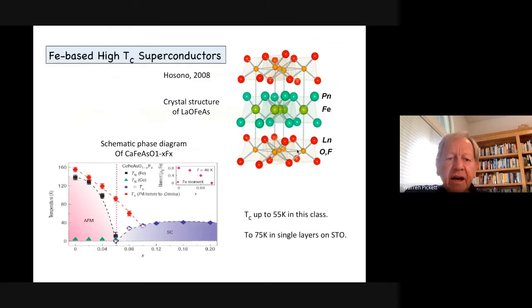Just mention iron-based superconductors here. It's unusual because we think of iron usually as being magnetic. And in fact, it is magnetic here. It's a weaker form of magnetism than in elemental iron. But you see here is an iron arsenide layer, another one up here, another one down here, and they're separated by these lanthanum oxide layers.